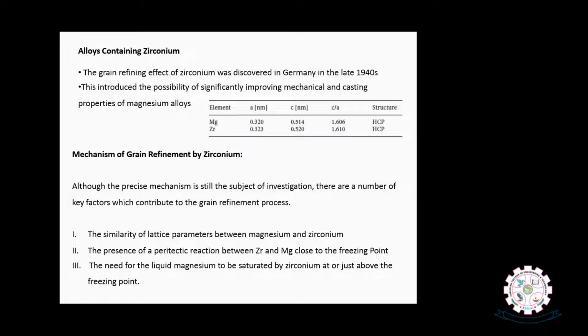The similarity of lattice parameters between magnesium and zirconium may be the reason behind the grain refinement that we achieve in zirconium containing magnesium alloys. Another finding is the presence of a peritectic reaction between zirconium and magnesium close to the freezing point. Another third reason contributing to the grain refinement when we add zirconium to magnesium is the need for the liquid magnesium to be saturated by zirconium at or just above the freezing point.